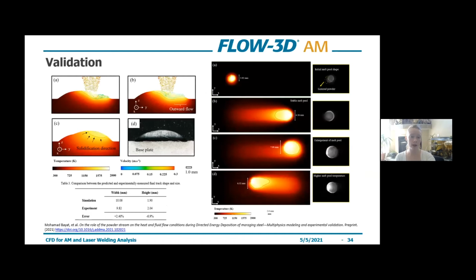Looking into their validation, what they did was compare the width and depth of the solidified bead, as well as the melt pool dimensions during the process itself. So looking at their comparison of the width and height of the bead, the error percent was about 1.42%, 6.9%, which is pretty good agreement in terms of comparing experiment to simulation.